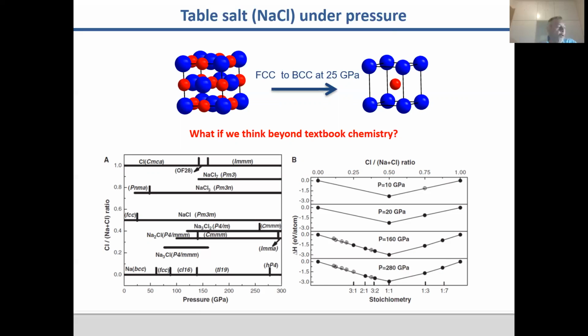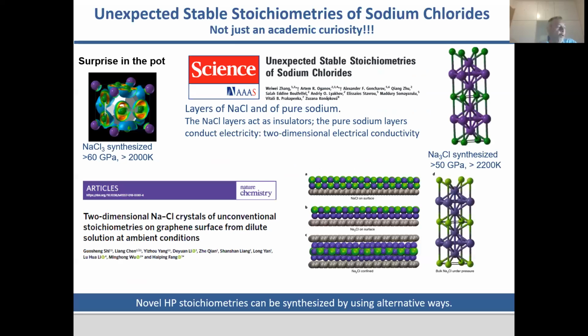Again, you can see the convex hull here that I discussed before. Of course, this is amazing to be true before you perform experiments. And indeed, we have performed experiments and we managed to synthesize both families of compounds, both the chlorine-rich and the sodium-rich, at about 50 GPa and after laser heating to 2000 Kelvin. And now, I think Maduri is attending the talk, so he may want to comment.